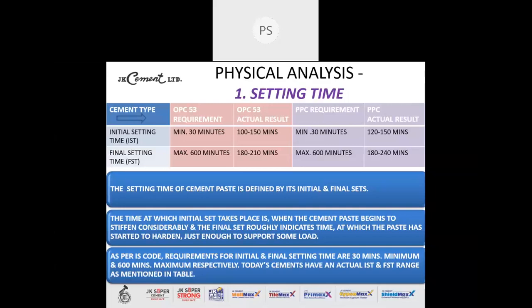Now, initial setting time, IST, OPC 53 requirements as per IS code is minimum 30 minutes, as you can see in the table above. The OPC 53 actual results in India is between 100 to 150 minutes. The final setting time FST maximum 600 minutes. कोई भी cement 600 minutes से ज़्यादा set नहीं होना चाहिए. It should have a maximum 600 minutes final setting time, and the Indian cements show a final setting time range of 180 to 210 minutes, about 3 to 3.5 hours.